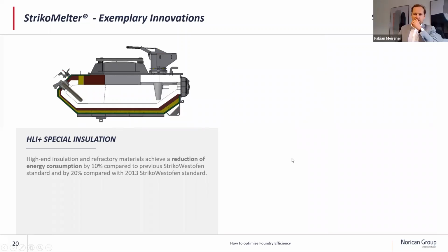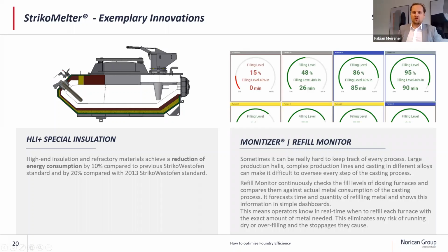Then we also have some new insulation for our furnaces. This is also one big difference to other furnaces. We have a very high quality special insulation which helps us to reduce energy consumption, and the release of our special insulation is achieving a 10% energy consumption reduction compared to our previous standard. And also here, like for the Striko Melter, we have a digital solution, which we call the Monitizer refill monitor.